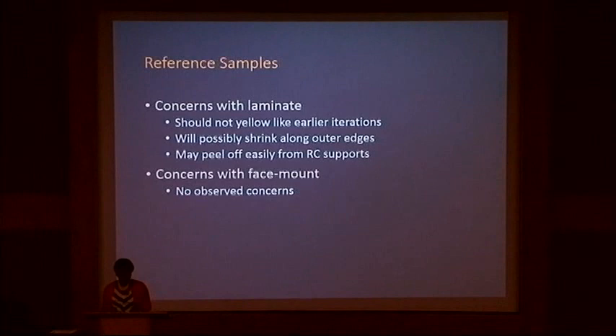As for material compatibility issues, it's been found that the laminate peels easily off of chromogenic print surfaces, but forms a more secure bond with inkjet print surfaces. And I interpreted this as a difference between a coated polyester or RC-based paper in the case of a chromogenic support and an uncoated paper in the case of an inkjet support.